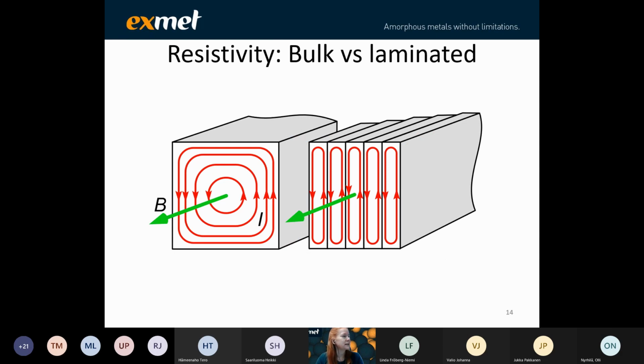Resistivity. Here we have an interesting situation when we are building large cross sections as we do in AM. Normally, by stacking, for instance, electrical steel sheets and laminating them, we can take care of eddy current losses, which limits these losses. This is a challenge when we build everything as a bulk, as we do in AM. We cannot laminate our particles in this manufacturing process. So we have a bulk instead, and the eddy current behavior is different.